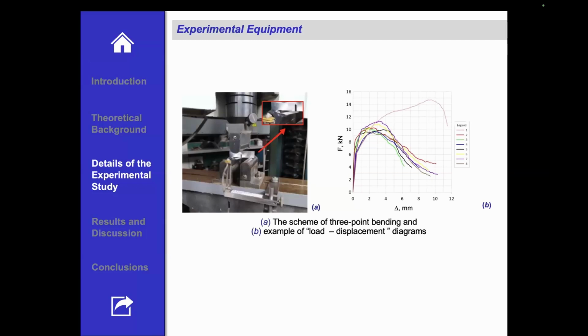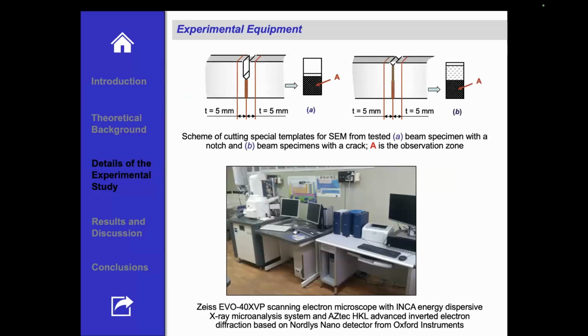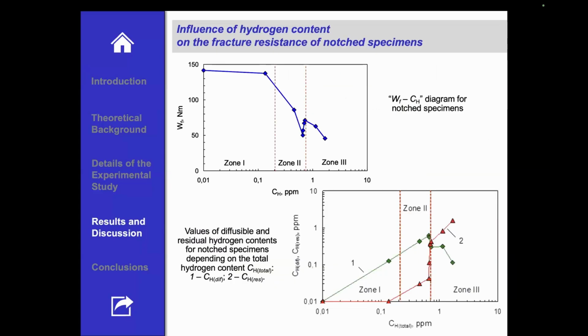After that we tested the material in air and pre-charged specimens, and as a result we have some groups of dependences. For the next step, the analysis. After testing, we used the scanning electron microscope for analyzing the fractured surface. And after the tests, we built diagrams of the parameter